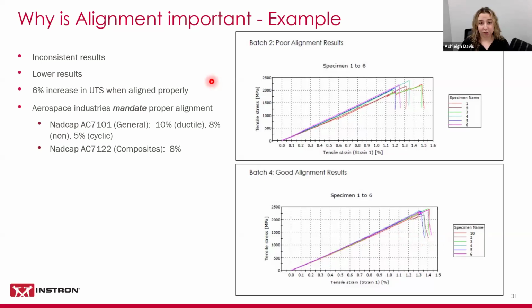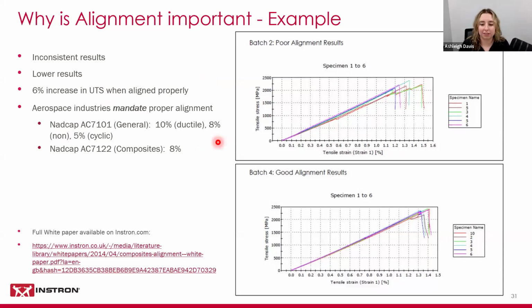In areas like aerospace, including NADCAP, they mandate proper alignment. So for metals, they essentially say 10% alignment for ductile, 8% for non-ductile, and 5% for cyclic. For NADCAP for composites, they indicate that the bending moment cannot be more than 8% upon initial loading. And as I said before, the lower graph was an average of 5%. There is additional information on our website regarding this testing via the white paper, so I recommend you check that out.